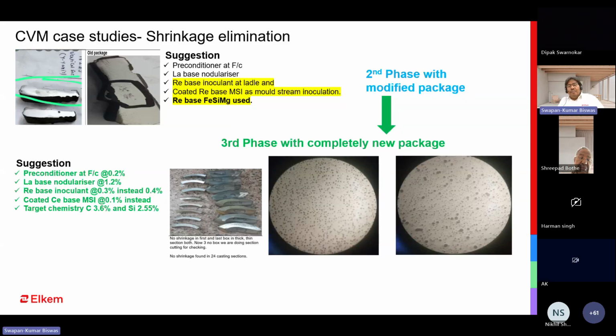But in other cases, maybe pig iron or silicon carbide, will give only a short period of effect. When the metal is maybe 6 tons and takes around 1 hour to complete the pouring, silicon carbide or pig iron will not give the effect till the last pouring. So in that case, definitely you have to decide on a longer-effect preconditioner. In the second phase, whatever we recommended, they partly used and partly decided themselves, but still there is the problem.